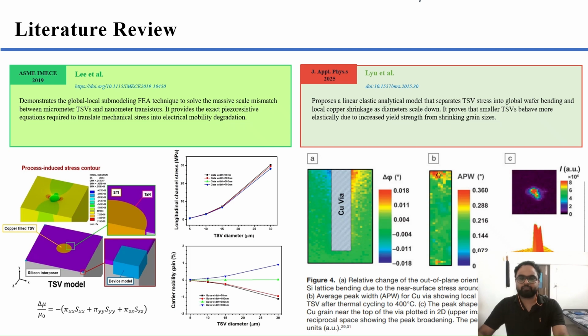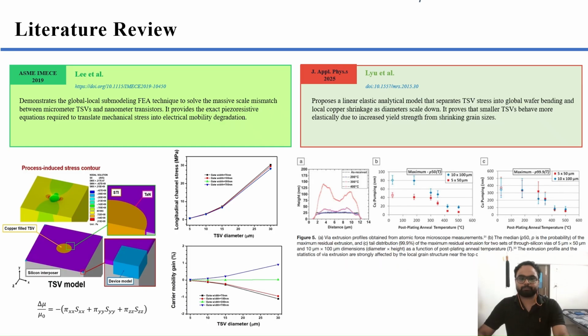The peak width of the X-ray peak is widest near the top of the via, shown in red, meaning the copper has undergone local plastic deformation. It has been permanently squeezed and distorted there. Panel C shows the X-ray diffraction peak shape in 2D and 3D. Instead of a sharp clean spike, the peak is broad and spread out, which is directly a fingerprint of internal stress and deformation inside the individual copper grain.